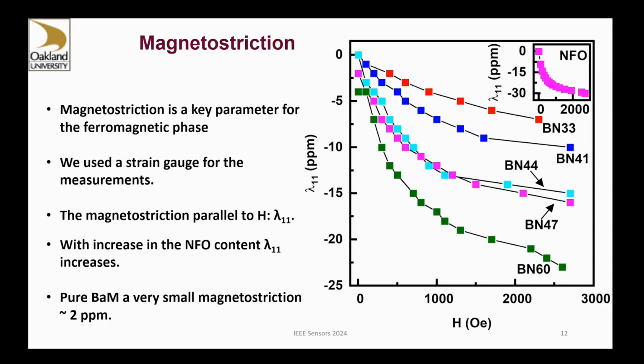So these are the magnetostriction for the spinel hexaferrite composites, and it's pretty good. I think the maximum value is around minus 25 parts per million. It doesn't quite saturate for fields up to 3 kilogauss. That's because there is a very large fraction of hexagonal ferrite.